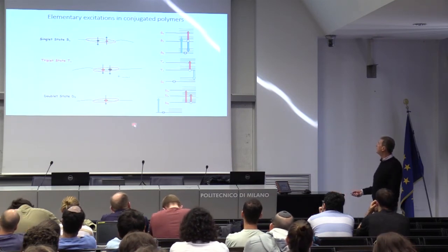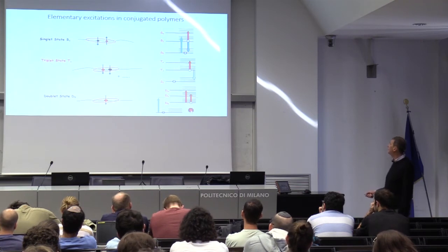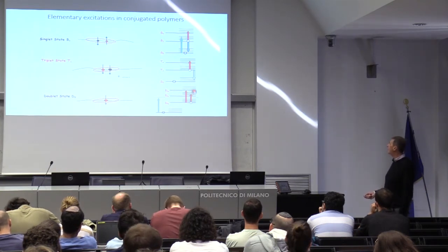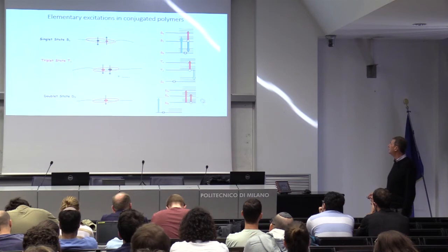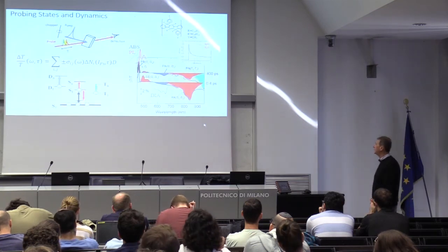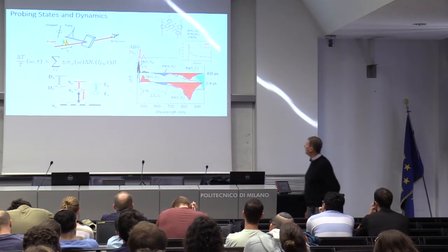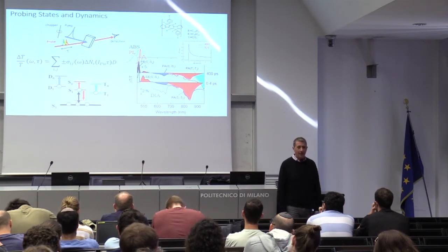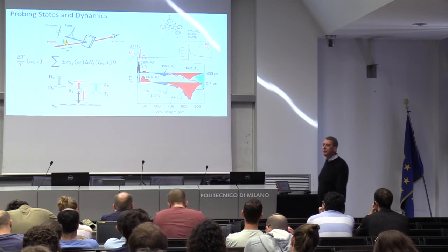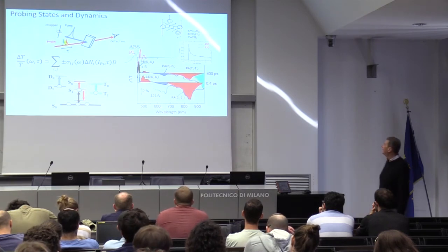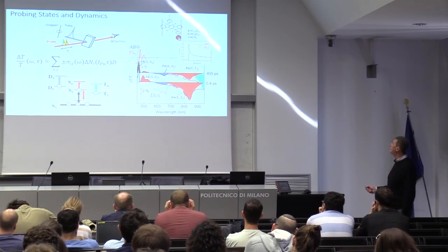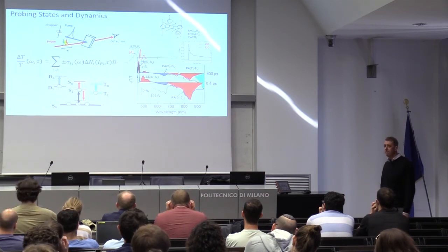And finally, if you have a charge, which you can form even optically, again you will have photobleaching because you are depleting the ground state, and a new absorption coefficient. Typically, the charge has zero coupling to the ground state, so you don't see stimulated emission. And that's an example. This is great. I forgot the reference, it's a Physical Review B, I think. This is a textbook case which happens once in a lifetime, and is my best experiment in pump probe. That is a polymer, it's a methyl-ladder type polymer.